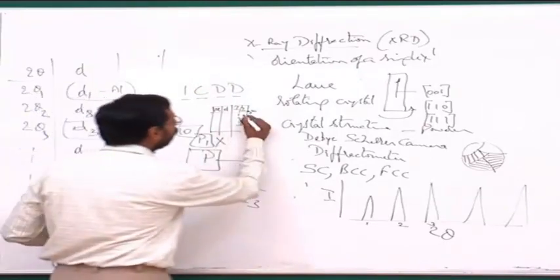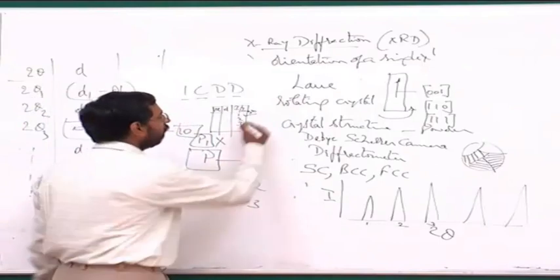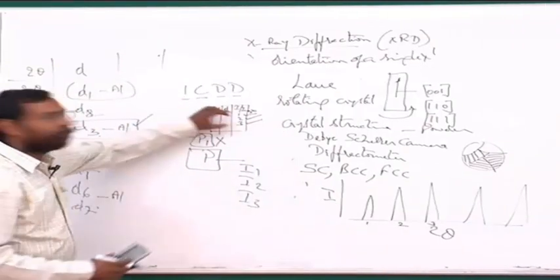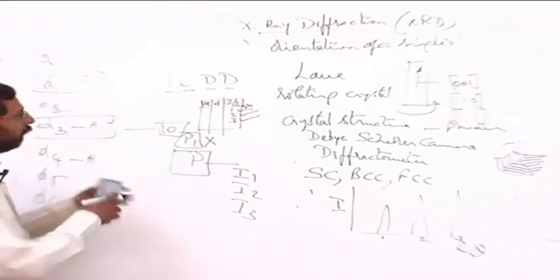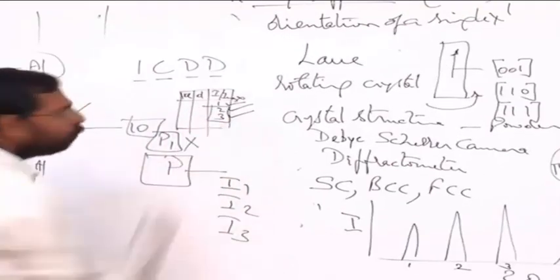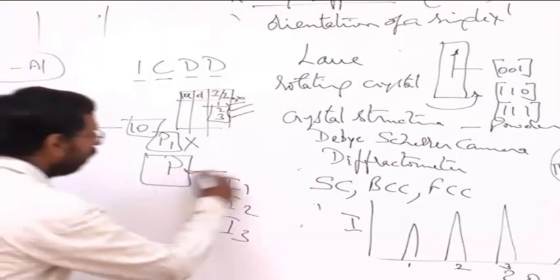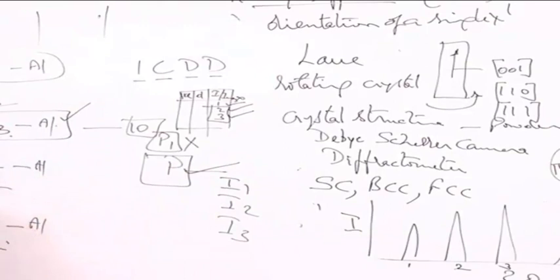What is more important is that I look at the most, second most and third most intense peaks, and check whether those 3 peaks are also there in our XRD pattern. If they are there, then I say this phase is there. If they are not there, I say no, this phase does not exist in my material.